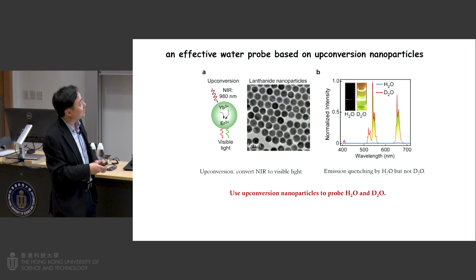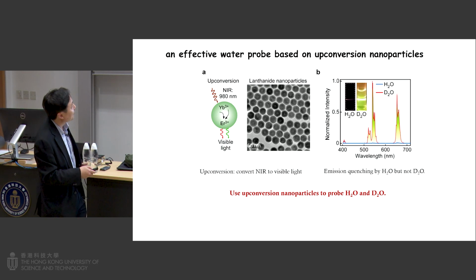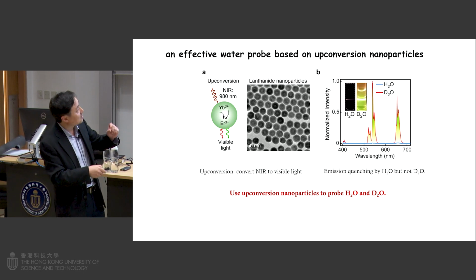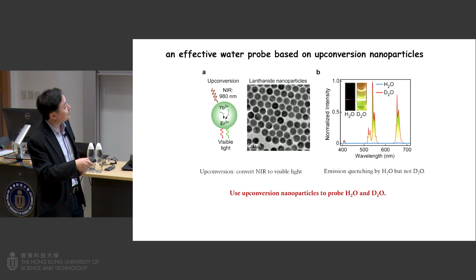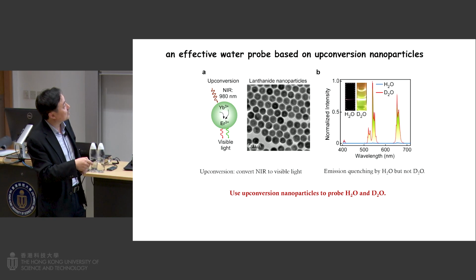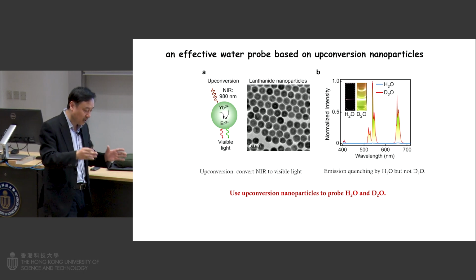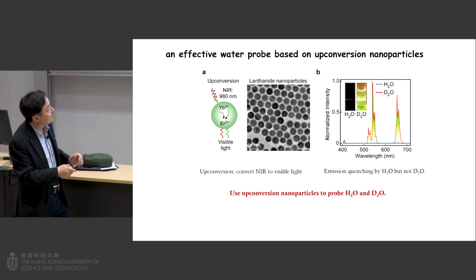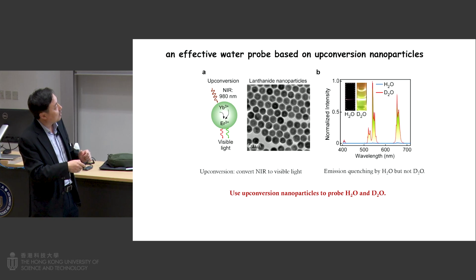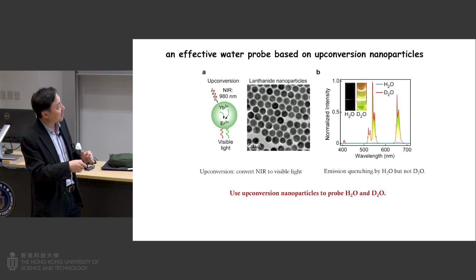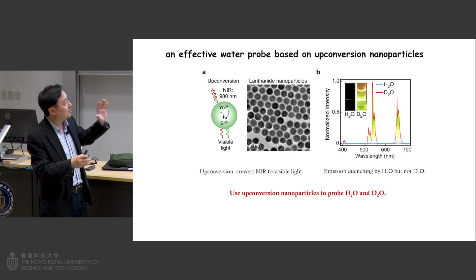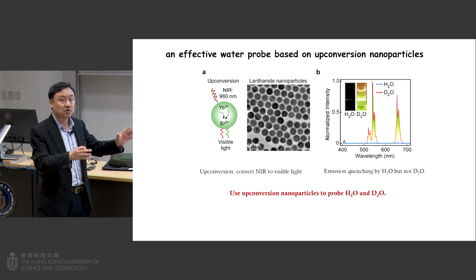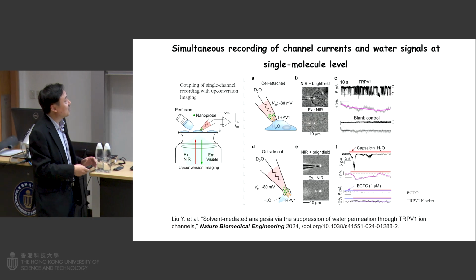So can we design some experiments using these photon upconversion particles? We designed this quite interesting phenomenon you can see here. In different solvents, if you disperse the particle in aqueous solvent, you can see the luminescence quenching. Most of the luminescence is quenched by water molecules. But if you switch to D2O, you can see the strong luminescence comes back. So this is based on this luminescence turn-on using two different solvents.